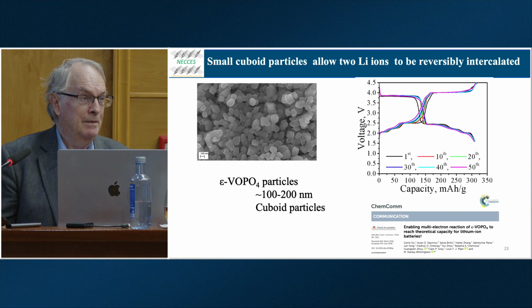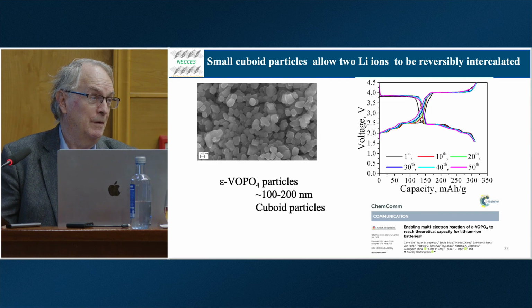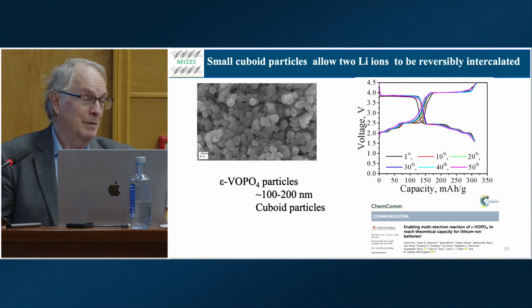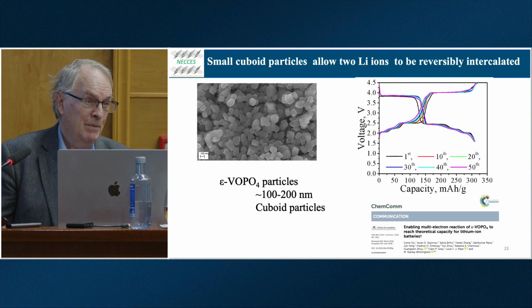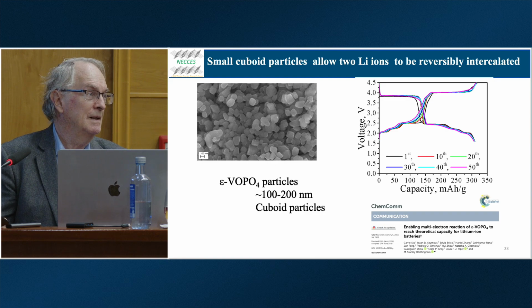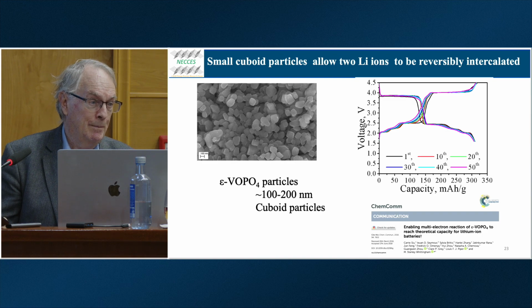So we've shown that these materials are stable, that you can in fact find host lattices where you can stuff it full of 2 lithium ions. We're trying to do the same thing with sodium now, so we can get the energy density up. And if we get this working perfectly, it will have the same energy density as those layered oxides and be much safer.